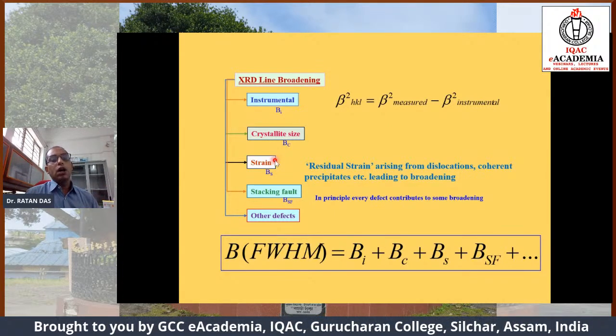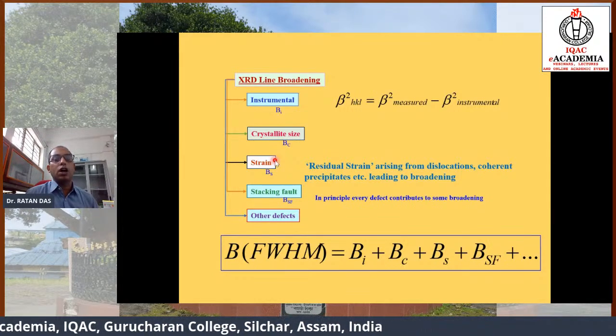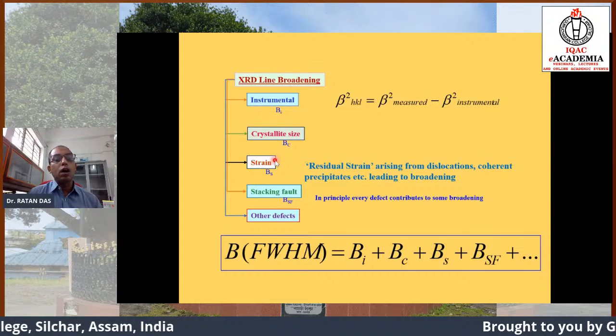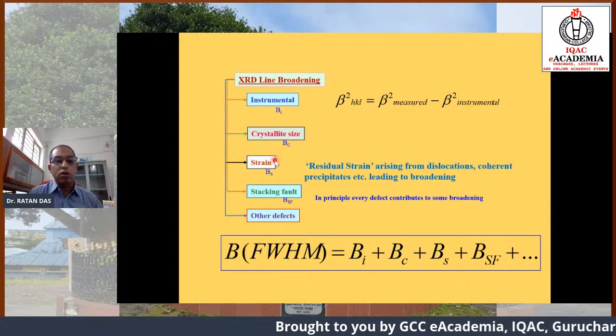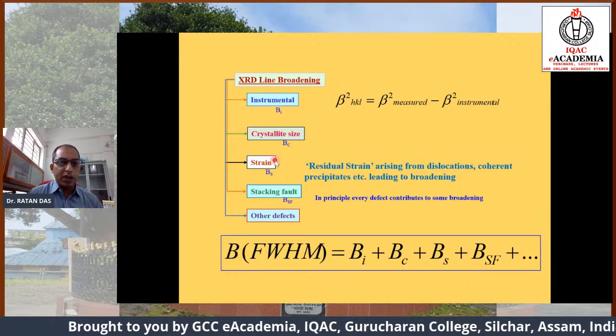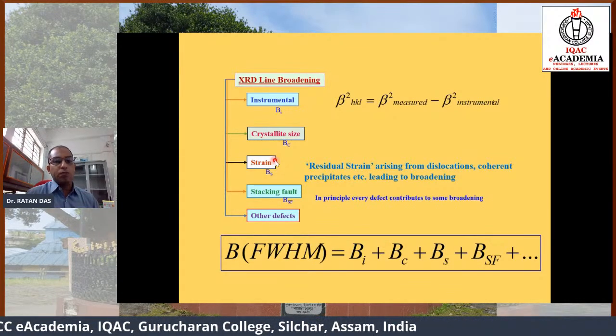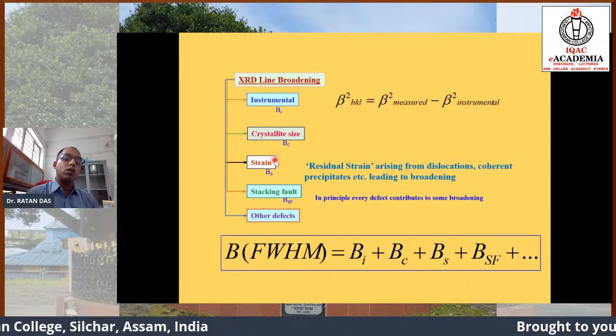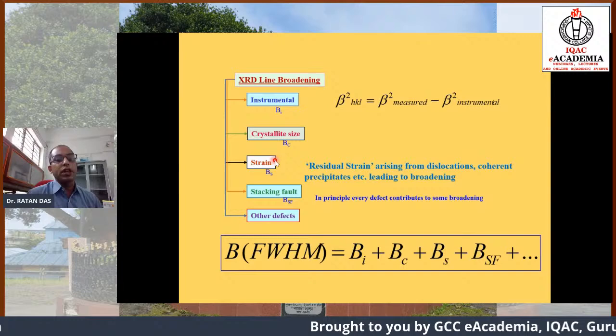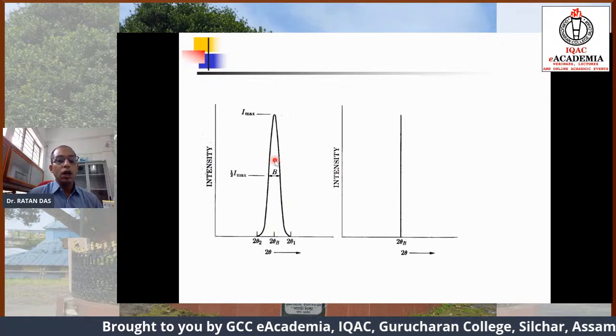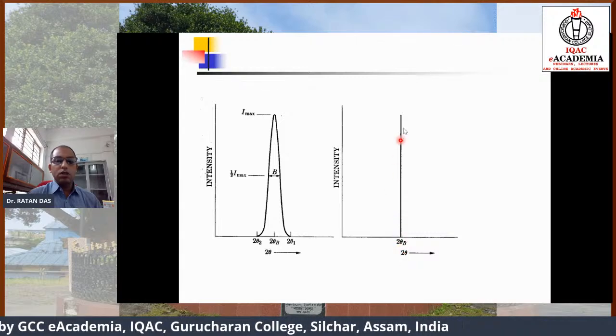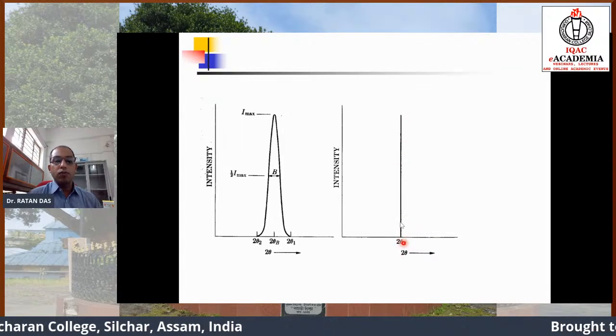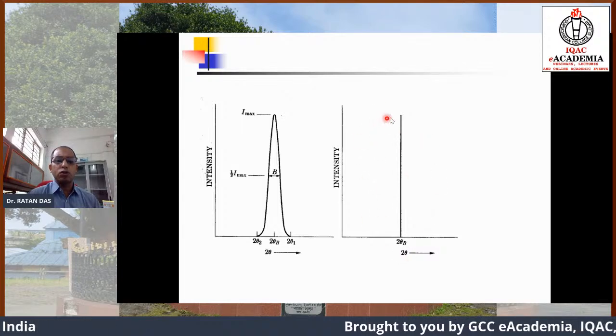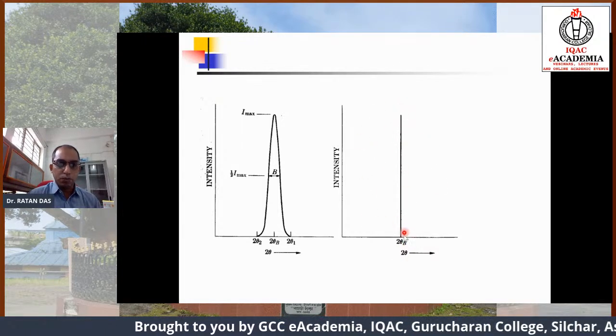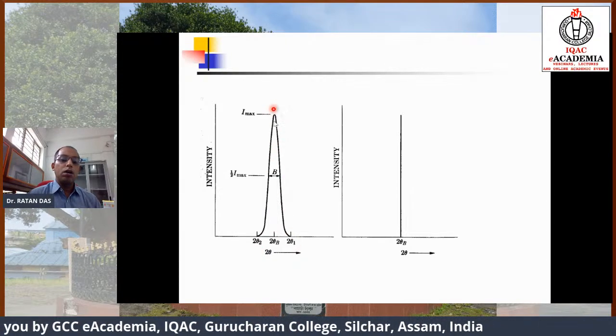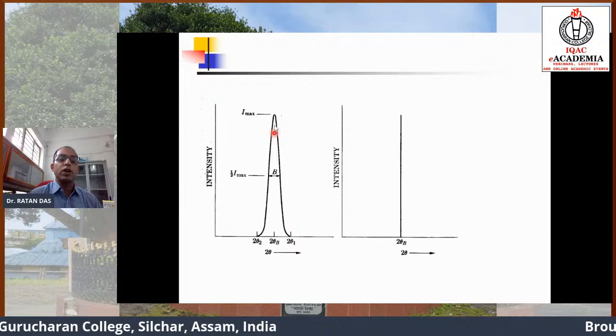And in the nano range, some extra strain comes into the picture because of the rearrangement of the atoms in the small region, what is called the size effect, or you can say the confinement effect. So because of the confinement effect, because of the size effect, we can observe some broadening in the X-ray diffraction pattern. Here you see this is the infinitely peaked pattern, this is a schematic diagram though. This is the infinitely peaked pattern that we obtain for a bulk sample, and this is the broadening of the X-ray diffraction pattern in the case of a nanoparticle sample.